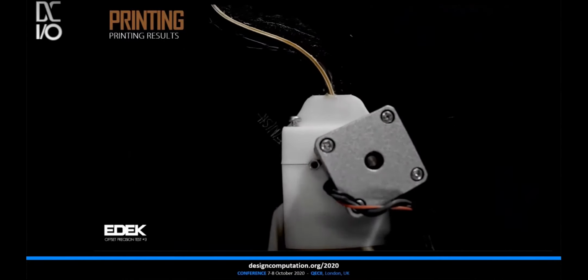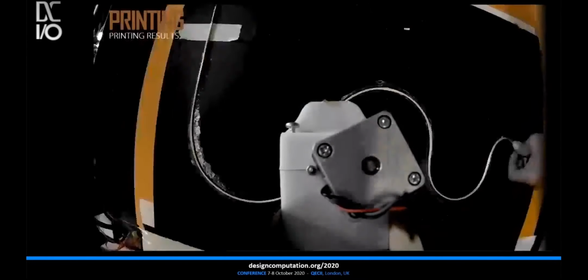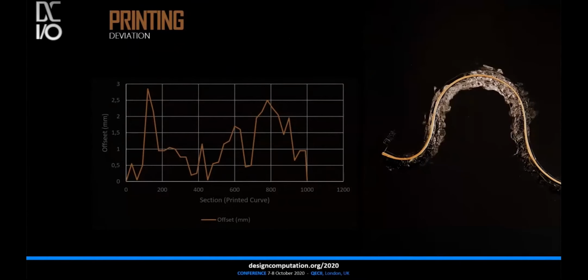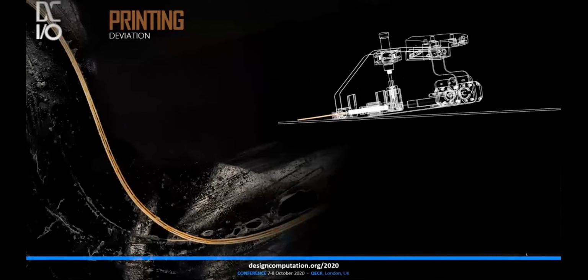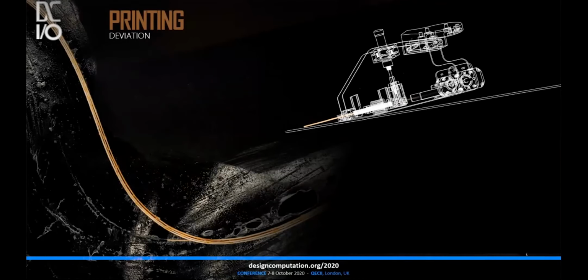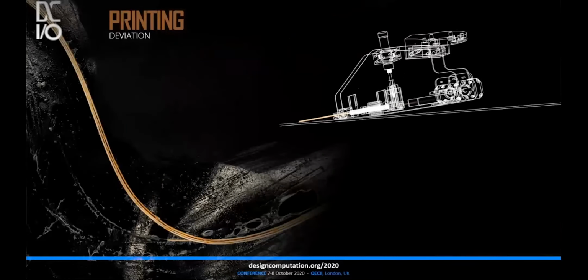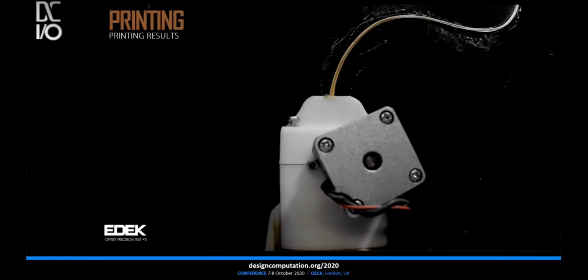The initial testing of the extruder provided promising results with only a small deviation. For a good first layer adhesion, the print bed was coated with a thin layer of the compound material. The printing angle, the angle between the extruding filament and the print bed, was set to 10 degrees to make good contact with the print bed while minimizing the distance between the nozzle and the print bed itself.